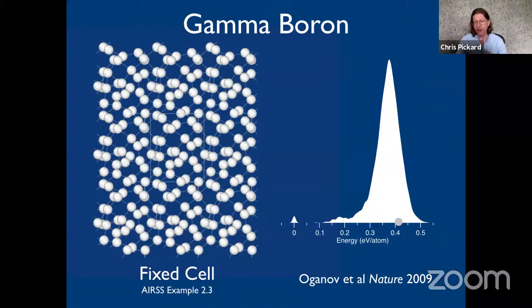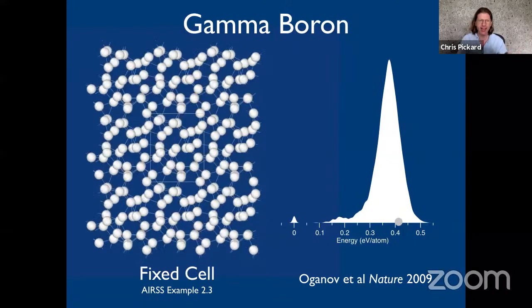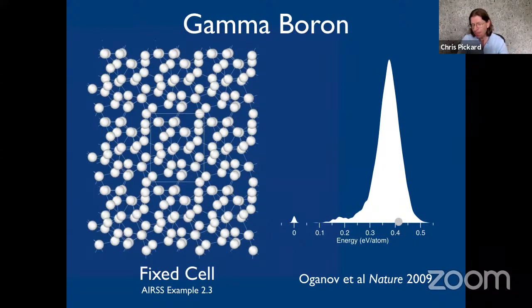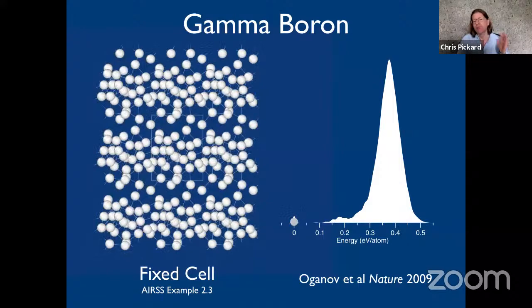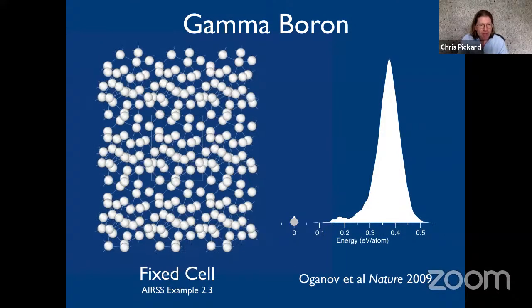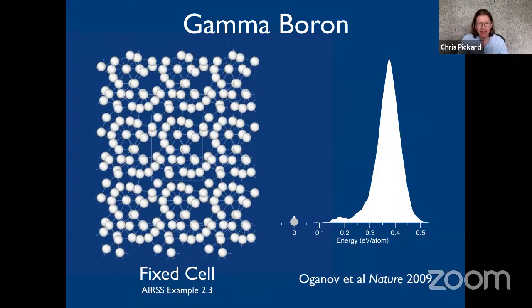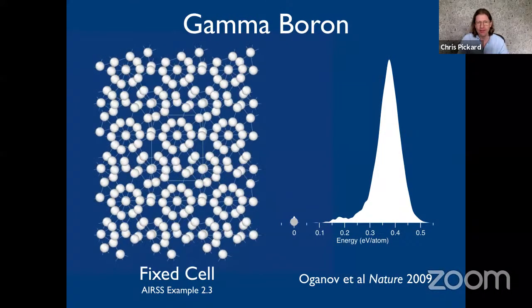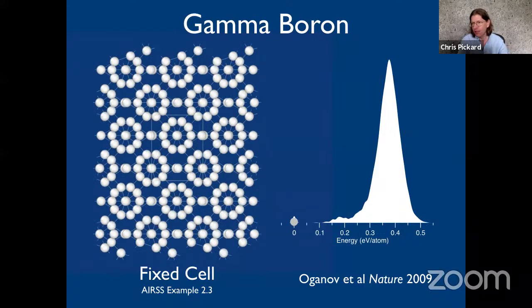So when you do one of these random structure searches, more often than not, you'll land up at something like 0.4 electron volts above the ground state, and the optimization will look something like this. So it starts off looking random and ends up looking rather random, lower energy. But about one in 200 times, which is fewer than needed for the evolutionary algorithms, you might start something like this. Again, looks very random. If anything, worse random. I don't know how you quantify that, but it doesn't look very promising to start with. But you relax the structure, and if you keep relaxing carefully, this is all with first principles methods, eventually it clicks into its beautiful structure. It's about one in 200 times.